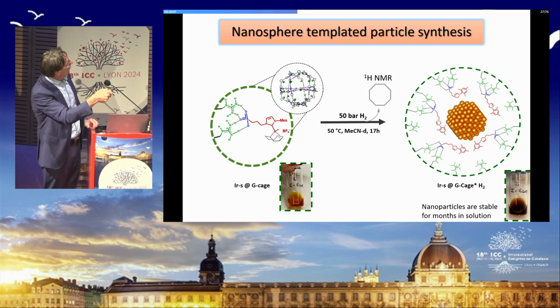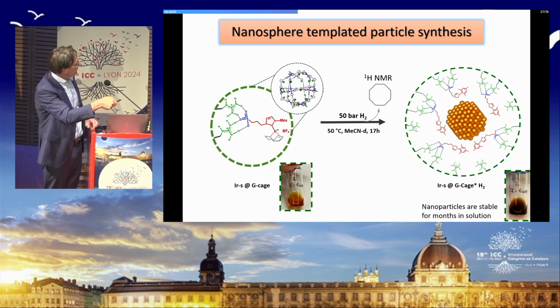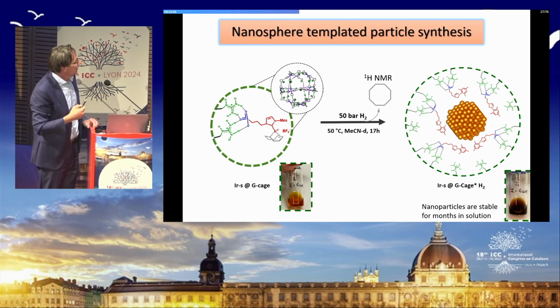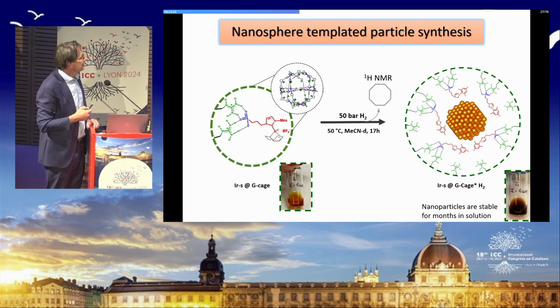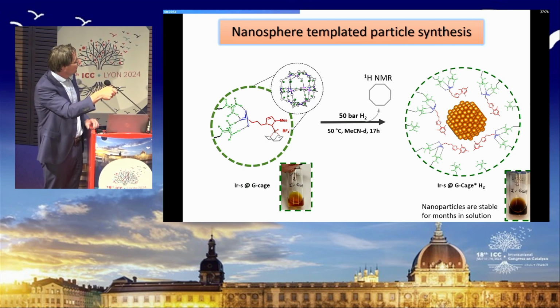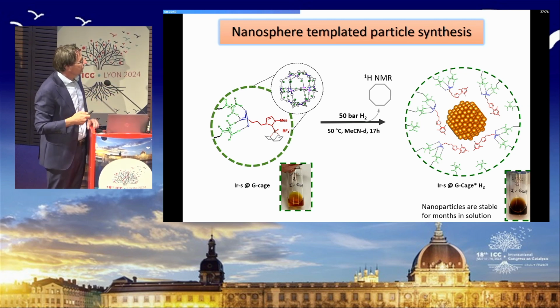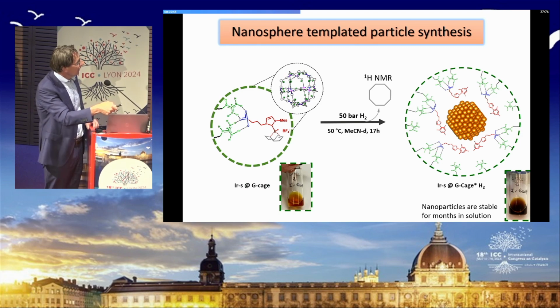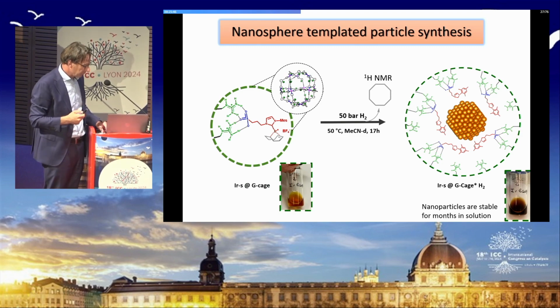Next, we apply reductive conditions. So this is the iridium complex in the cage, and this is after reduction. So after reduction, we see by NMR the cyclooctane that comes from the cyclooctadiene, in line with reductive conditions, and this nanoparticle should be formed.